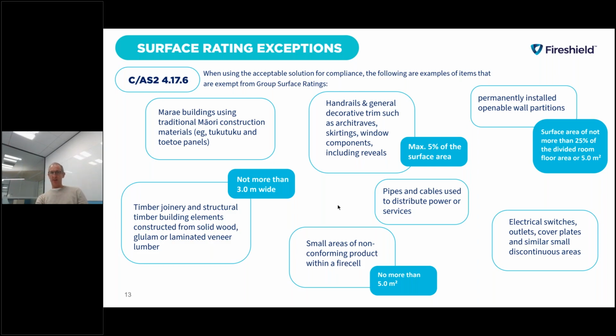Now, because it was more than 5% of the wall area it was attached to, it actually required a group rating, which we can do by impregnating the timber, but you shouldn't really use a coating on it with human oils, impact from the hands. It would wear off over time, so impregnation is the way to go. But that's the solution there. You can see there's a whole lot of different exemptions, but this is only for if your design is using an acceptable solution. So if the fire engineer has done a specific design, they'll have to consider these individually if they've modeled the design.